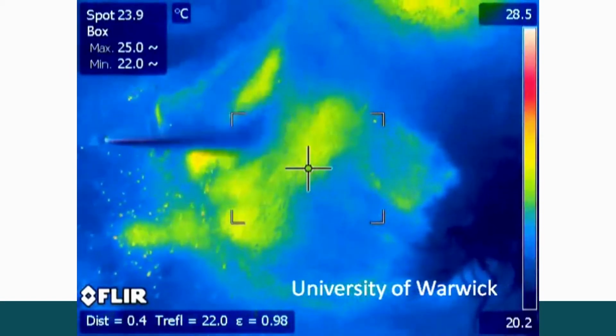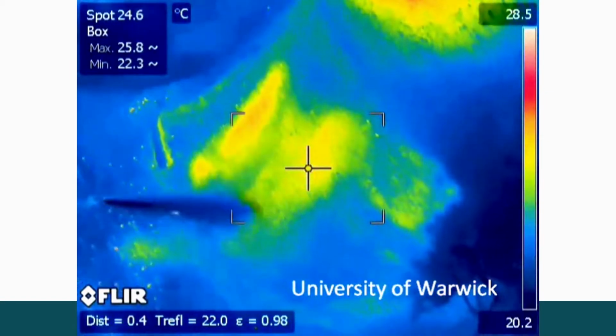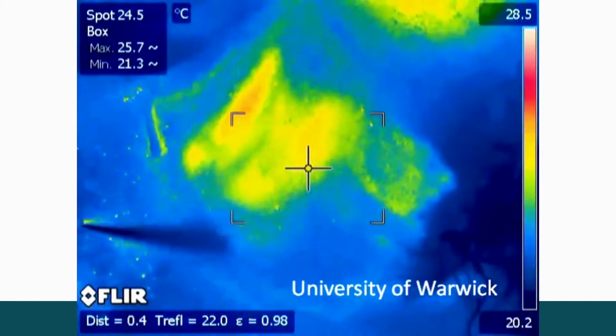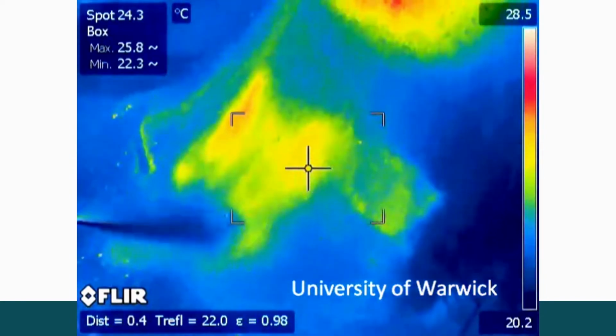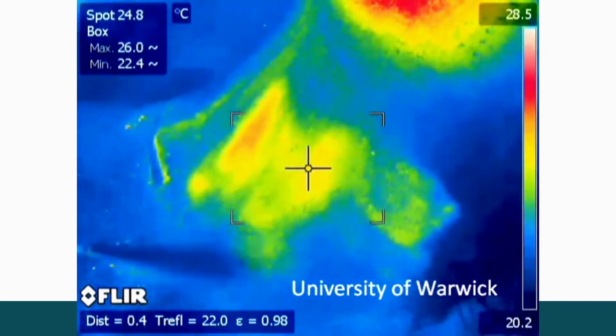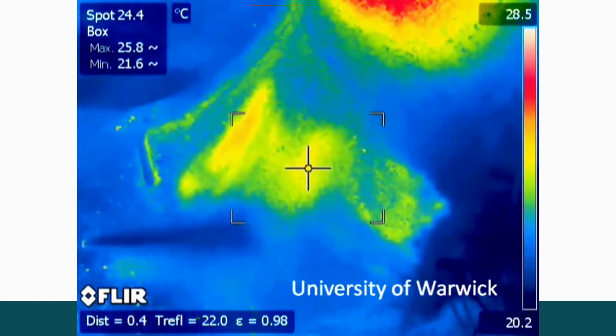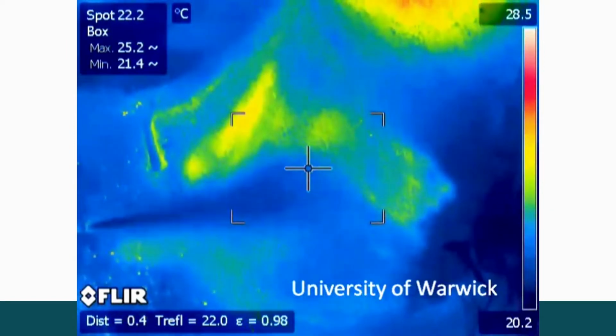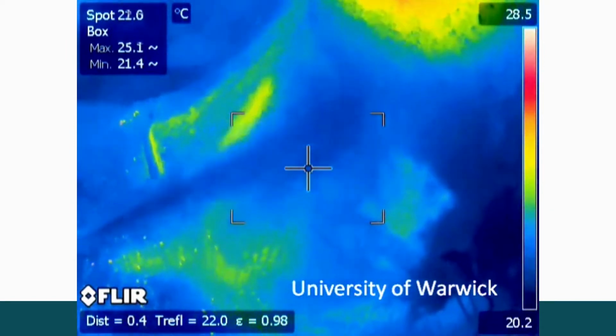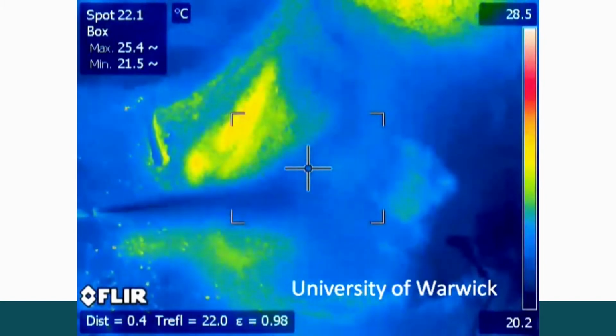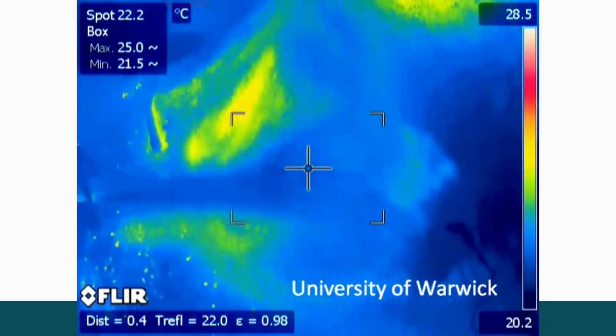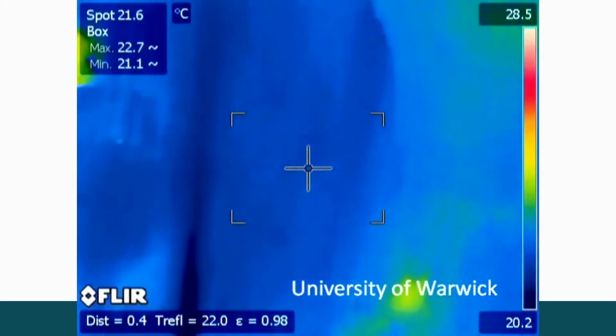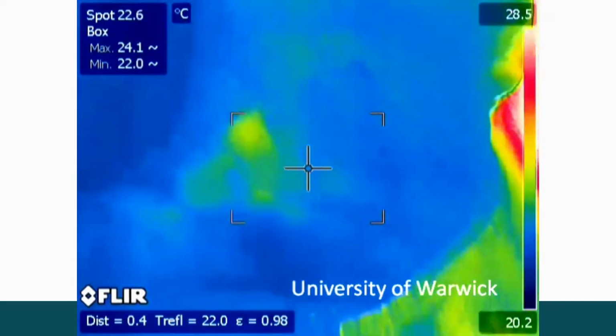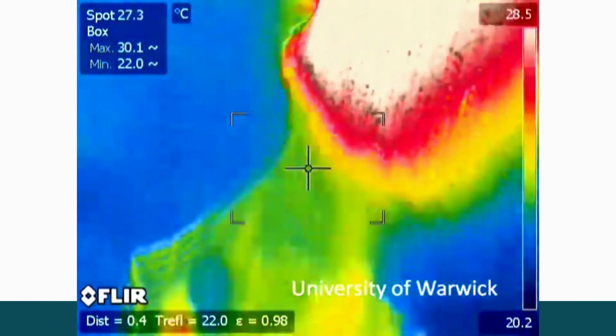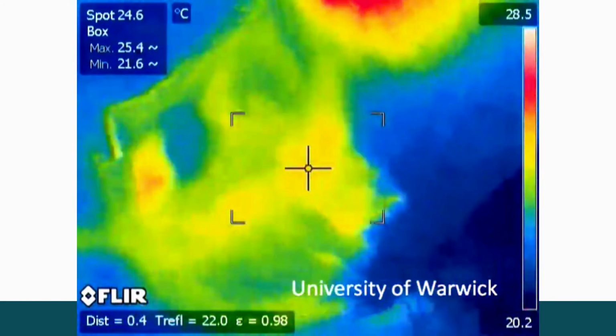And here's a picture of actual spraying. This is spraying of that right-hand bench bit. You can see the stream of shotcrete from the nozzle is about 20 degrees, which is typical for fresh concrete batched on site, in London, any time of year really. And pretty soon after the shotcrete hits the wall, it's already going yellow, which means it's going up a few degrees.